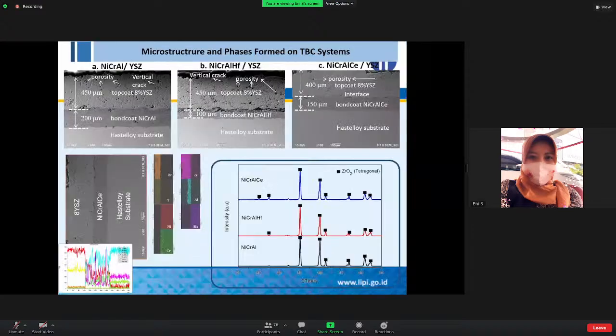This figure shows the cross-sectional structure of the coated sample before oxidation. The coating is composed of two layers, a metallic bond coat and a ceramic top coat. The coated layer was established at approximately 450 micrometers for the ceramic top coat and around 100 to 200 micrometers for the metallic bond coat.